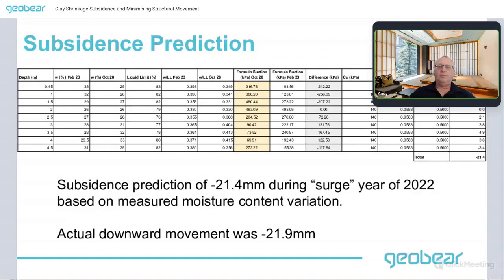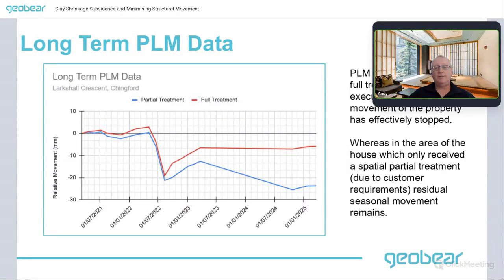On this particular model, there's a prediction of about 21 millimeters of movement based on the change in moisture content. And that was against an actual downward movement of roughly the same number, which is shown on the following graph. So here, what we're talking about is a prediction of this change in settlement of about 20 millimeters. This directly corresponded to the change in moisture content that had been measured.